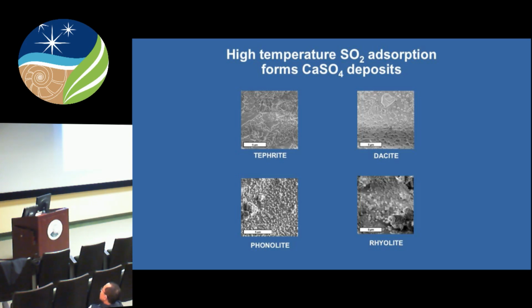But of course, when you react these things with the exterior gas, basically two possibilities. There's some diffusive exchange, which is on a very, very fine scale, and I don't want to talk about XPS measurements too much because it's not my favorite thing to do. But we had a lot of arguments about the nature of, and you may know there's a long discussion in the geological literature about the surface of basaltic glass and what's really going on, what's diffusing where, and some counterintuitive results. There's the diffusive interaction. This is still 600-700 degrees Celsius.